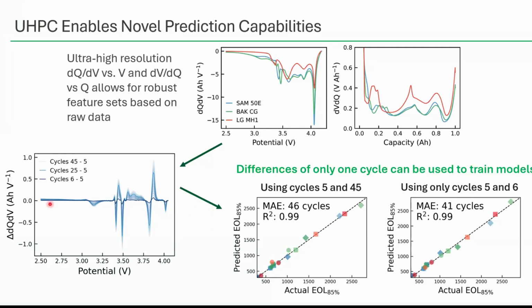amount of time. We can already see that cycles 5 and 6, this residual difference in this one cell, all of the features are there. They're just quite small. If we use only the cycle 5 and 6 difference versus the cycle 5 and 45 difference, the predictive behavior of the models is actually basically the same. So just in using the difference between a couple cycles, it's fairly miraculous. We're able to predict the lifetime of these cells in these very different conditions.